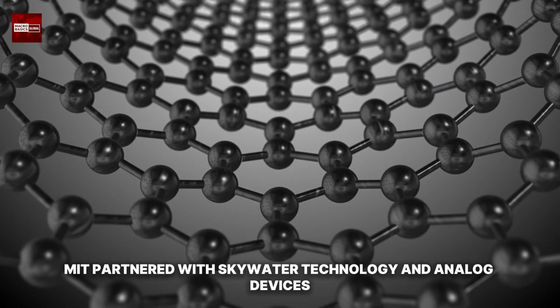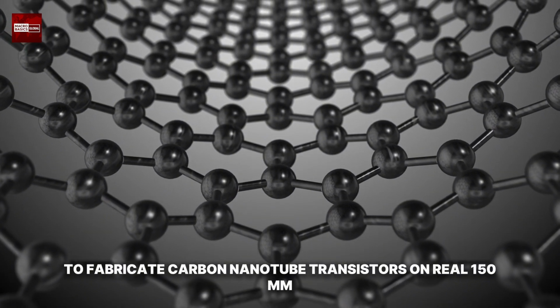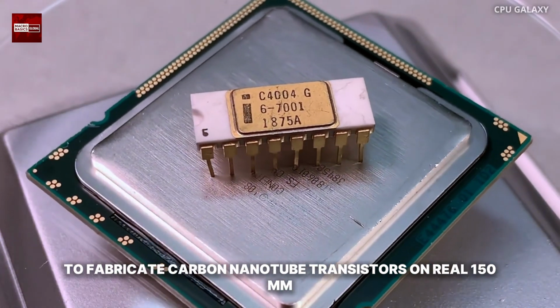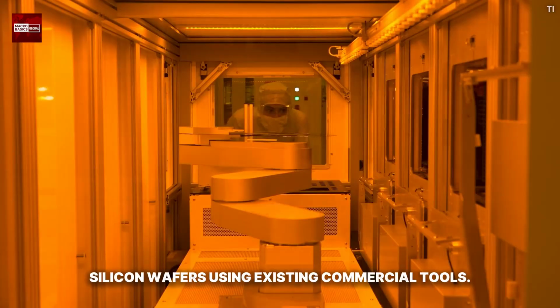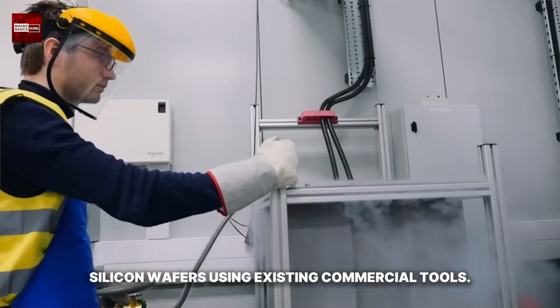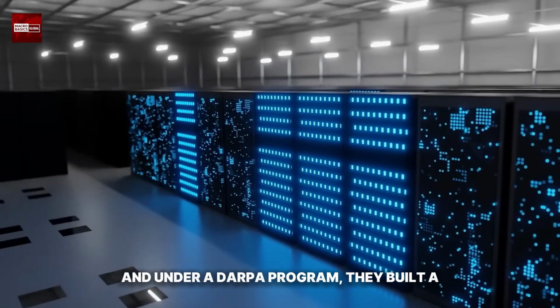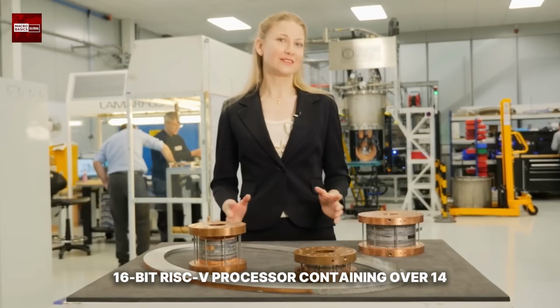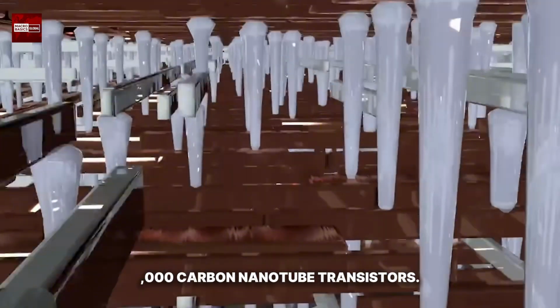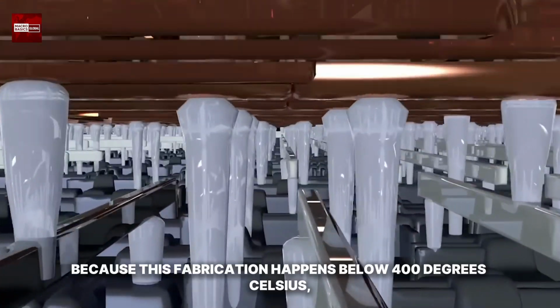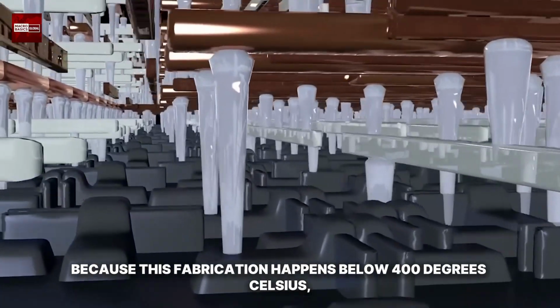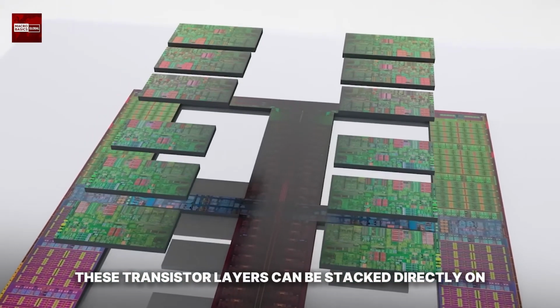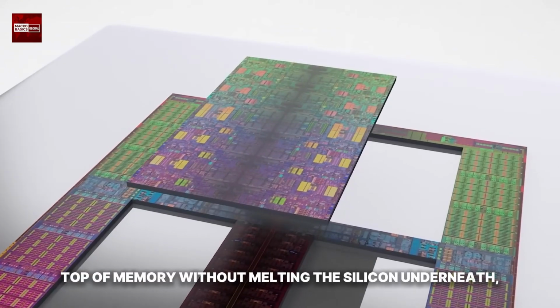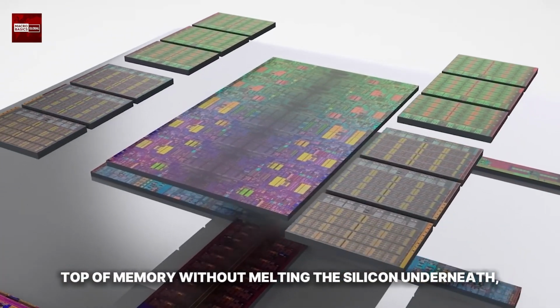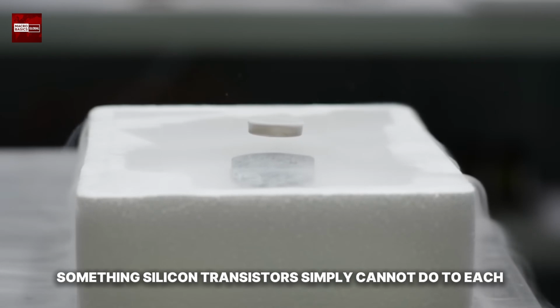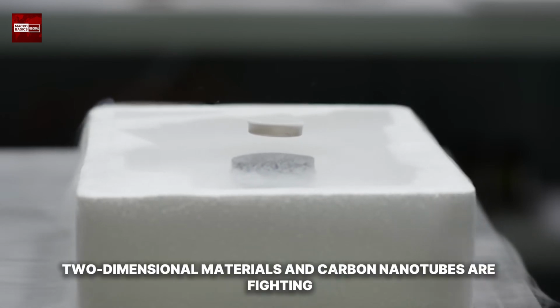MIT partnered with SkyWater Technology and Analog Devices to fabricate carbon nanotube transistors on real 150mm silicon wafers using existing commercial tools. And under a DARPA program, they built a 16-bit RISC-V processor containing over 14,000 carbon nanotube transistors. Because this fabrication happens below 400 degrees Celsius, these transistor layers can be stacked directly on top of memory without melting the silicon underneath, something silicon transistors simply cannot do to each other.